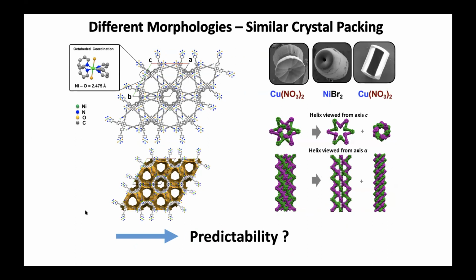The crystals consist of 2 types of channels. The diameters of the channels are about 1 nanometer. The inner walls of the channels are chiral, and inside one crystal you have the same chirality. So you have a racemic mixture of crystals, but each crystal by itself has its own chirality. And it's interesting to see that we start with achiral molecules. We use no chiral components to get chiral crystal structures.